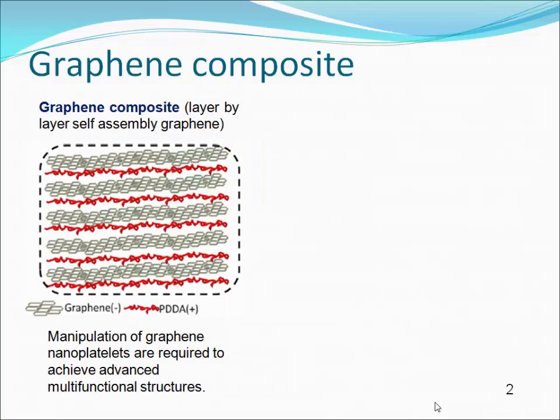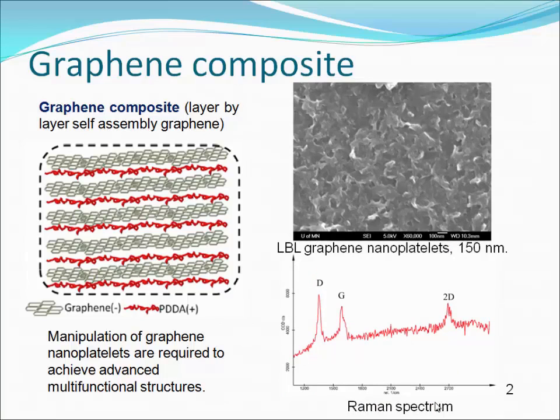So besides intrinsic graphene, people also try to integrate the graphene nanoplatelets with other materials to get advanced multifunctional devices and structures, such as a layer-by-layer self-assembly graphene. It has a layer of PDDA polymer at the bottom, which is positively charged. It has graphene nanoplatelets, which are negatively charged, another layer of PDDA, and another layer of graphene, this sandwich structure. The SEM image on the right top shows clearly this layer-by-layer graphene film.